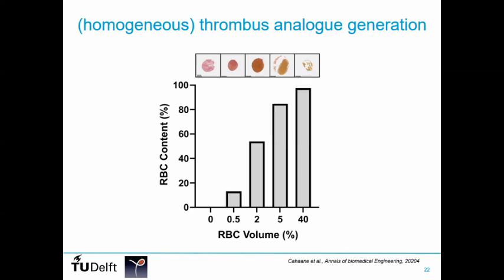Which means that during the process of forming the network, or forming that thrombus, that process is very efficient in capturing almost all red blood cells that you put in. And you can see that also because the fluid that is left over is nearly transparent. So during the process, all the red blood cells that you add are basically captured by that network.